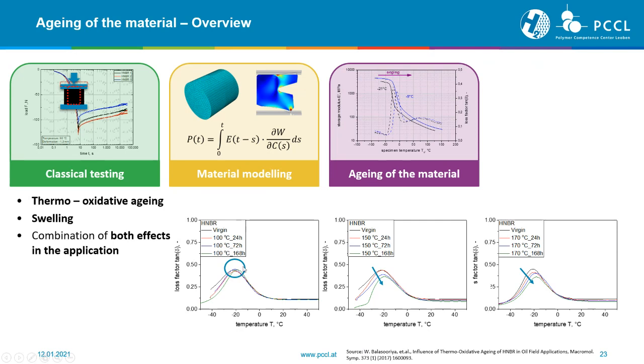At 100 degrees C, with 24 hours, 72 hours, and 168 hours, we see not that much impact. With 150, the impact already starts. The black and red curves are nearly the same, but the blue and green curves are already going down, which means on the one hand that the damping of the material changes, and on the other hand, when you look at the maximum of the loss factor, that the glass transition temperature is shifted to higher temperatures. And with 170, we see this even more pronounced: already with 24 hours at 170, we see a strong difference to the virgin material behavior we found for HNBR.